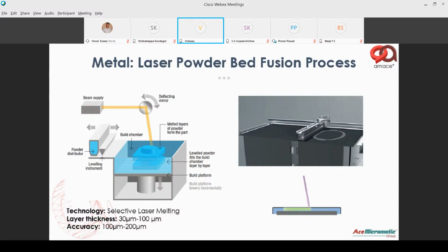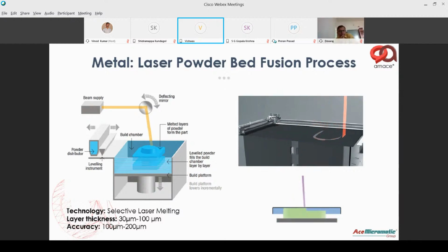As every layer is completed, the platform on which this is printed goes down, and the next layer of powder is laid. You can see on the left side, the blue image shows multiple layers of the powder that were fused to form the part, which is sitting in the middle of a big cake of powder. This layer of powder could be anywhere between 30 to 100 microns thick to get your part, which is finally almost finished. So this is basically how it happens.